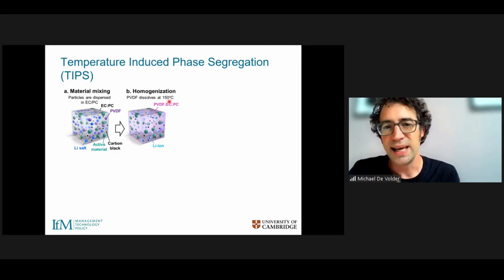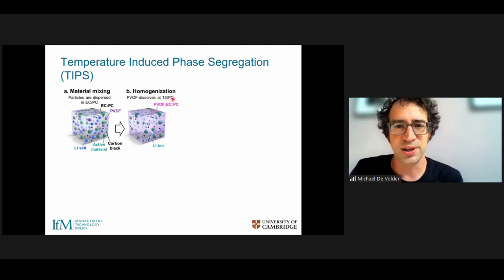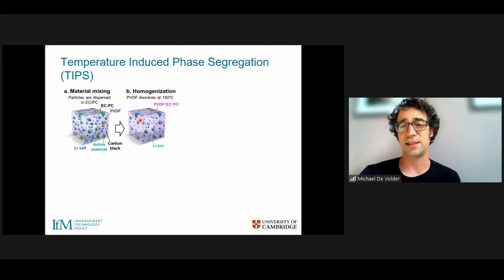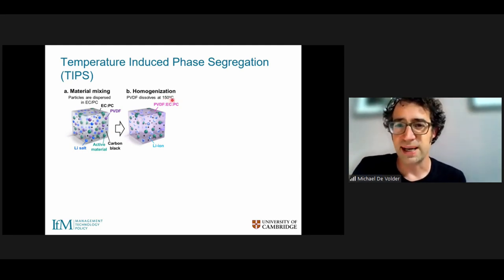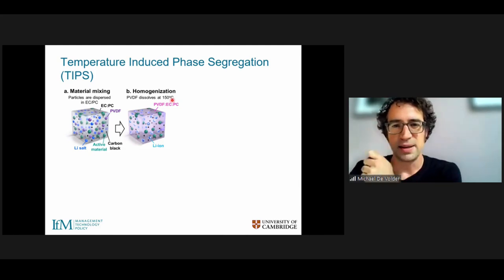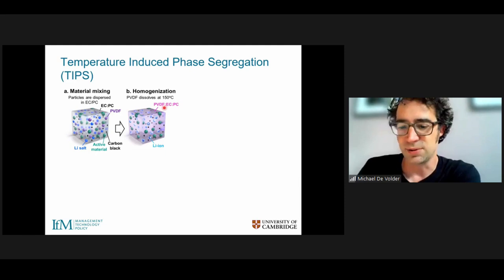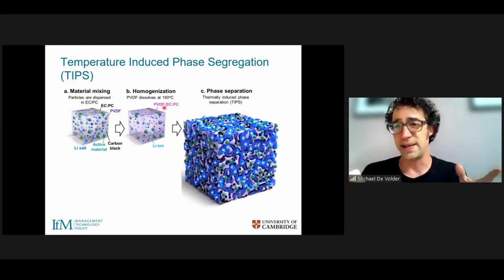We mix them all together, heat them up to 150 degrees, and what happens at high temperature is that the PVDF will perfectly dissolve homogeneously in the solvents. Now, if we then cool the suspension back down to room temperature, the PVDF no longer dissolves in these solvents, and it will form this phase segregation process I just described.